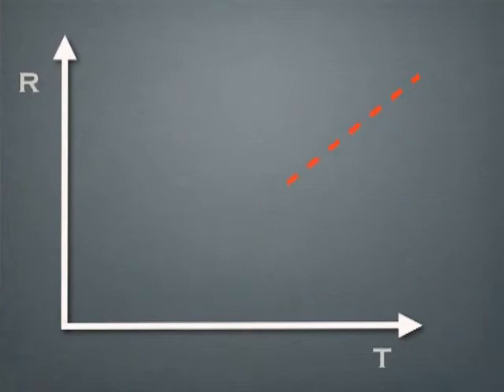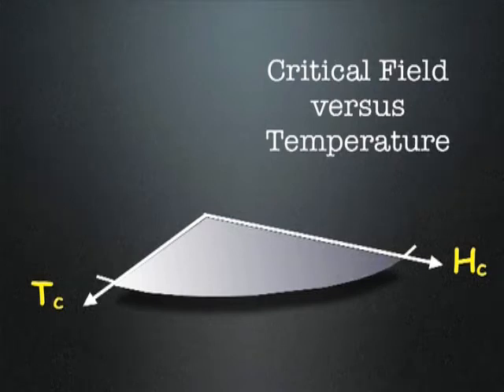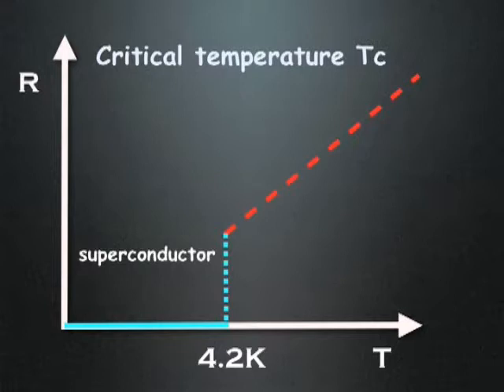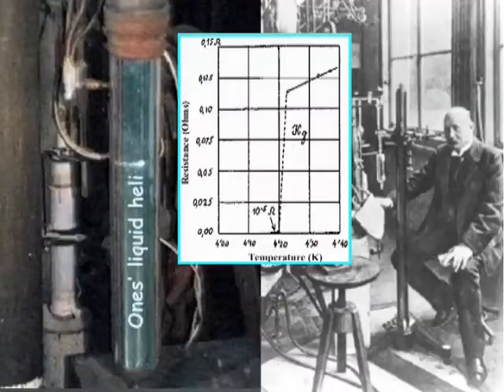Nevertheless, Kamerlingh Onnes recognised that besides this beautiful graph, there is another unpleasant dependence: the critical temperature as a function of magnetic field. The transition from a normal metal to a superconductor occurs at the transition temperature Tc, and with a very weak magnetic field it appears to be quite sharp, as Kamerlingh Onnes and Holst found back in 1911. With mercury, it has a resistance above 4.2 degrees, and the moment you get below that critical temperature, the resistance disappears entirely.